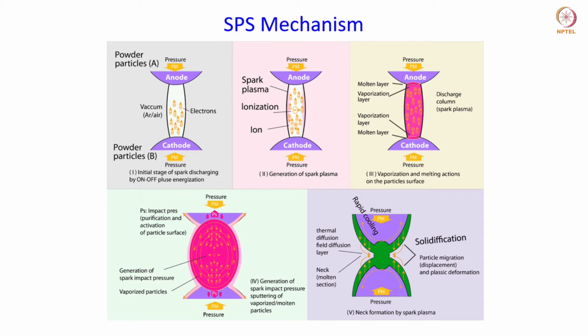Now this is a diagram which again shows the different phenomena that occur during the SPS process from beginning to the end. So in the beginning, when the electrical field is applied, a potential difference is generated between the particles, as if they are acting as two electrodes, which can have flow of electrons in between them. Okay, and therefore this has to be done in vacuum, otherwise this kind of electron flow cannot happen. So this is a two particle model which is depicted over here to demonstrate the phenomena and the mechanisms of the SPS process. So this is in the initial stage of sintering, by that on-off pulse energization which occurs as the electric field is applied.